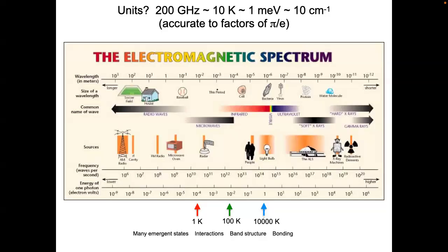again, like cuprate superconductors. If I have magnetic systems built of maybe more localized orbitals, let's say 4f systems, relevant in the heavy fermion systems and some interesting pyrochlore magnets, the exchange energies are going to be much smaller, milli-eV scales. Tens of milli-eVs ends up being an important energy scale in many systems for the phonons. Those are optical phonons, of course. The phonon scales persist down to much lower and, in fact, zero frequency if we're thinking about acoustic phonons.